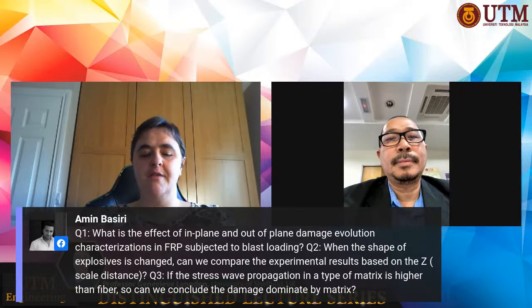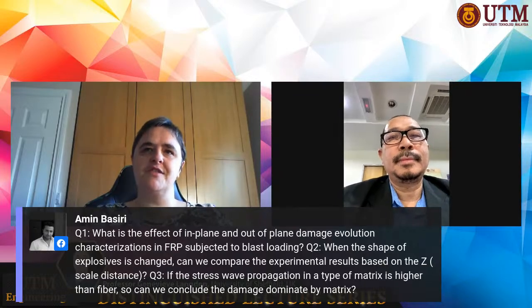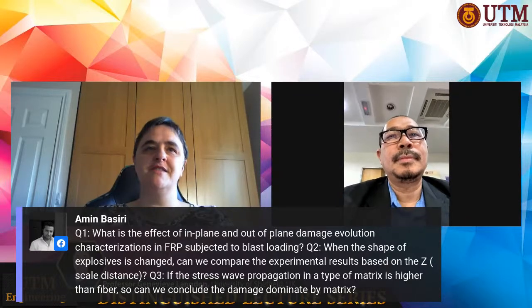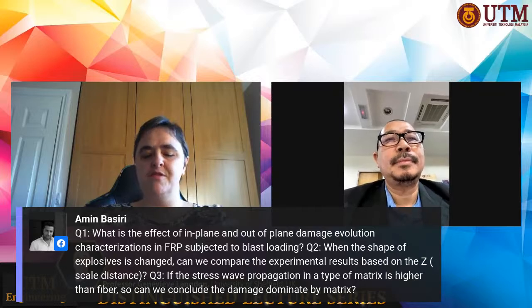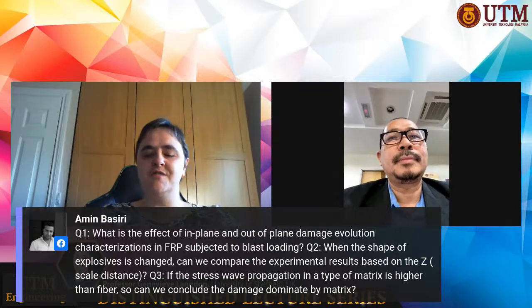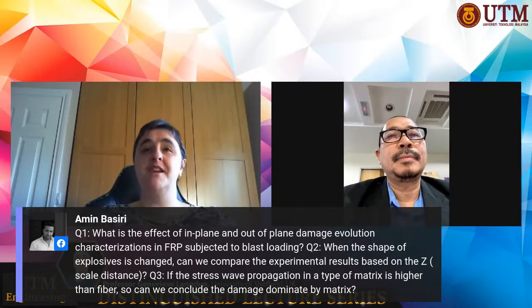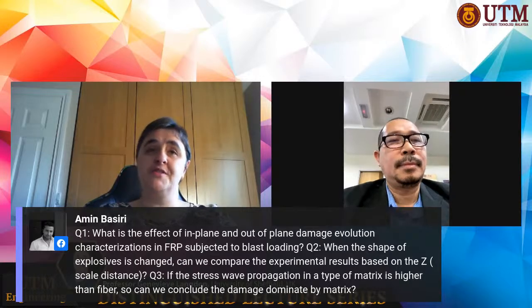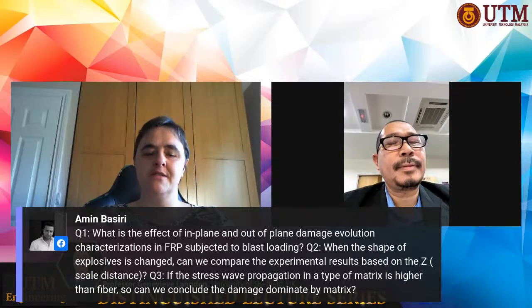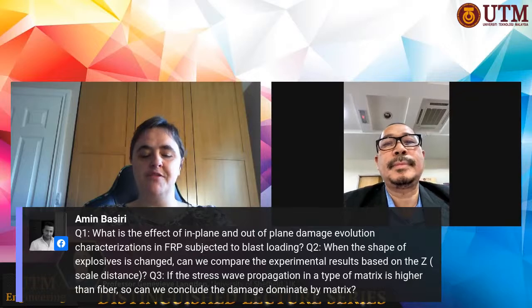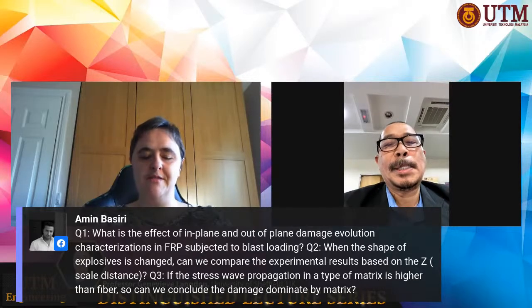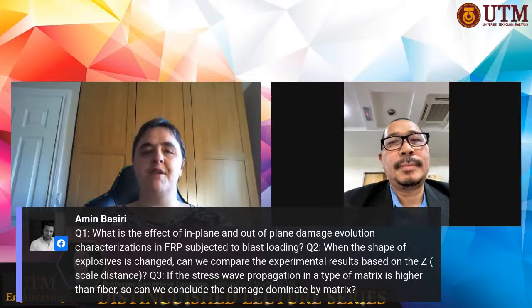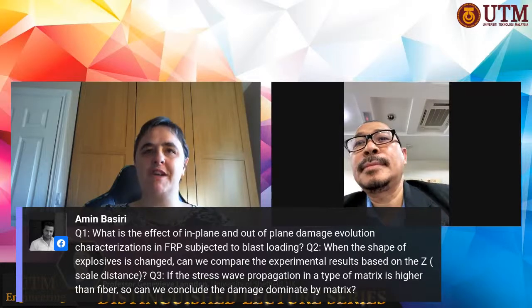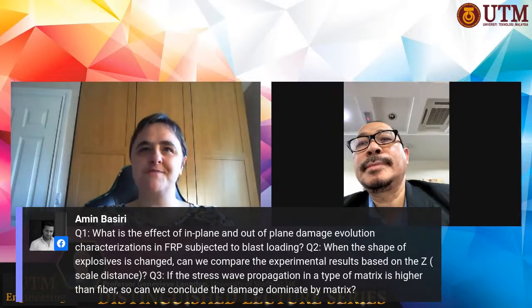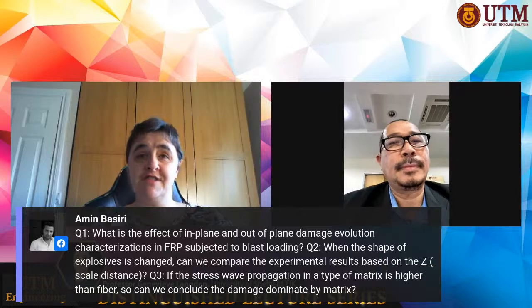When we tried shifting the fibers so that they were plus minus 45 degrees to the edges of the panels instead of 90, we were able to shift the orientation of the damage, which had typically been in a diamond shape. We were able to shift that through 45 degrees as well, because the debonding of the outer layer of the metal was affected by the stress wave propagation through the fiber matrix, which was a really interesting result.